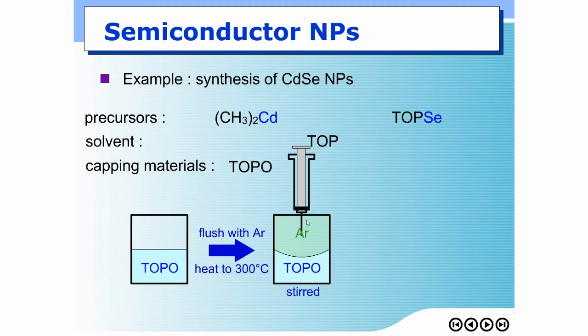So that means once this mixture experiences this high temperature, it initiates the reaction right away. So this is how we achieve high concentration of growth species, or how we control to get abrupt increase in concentration of growth species. Okay?